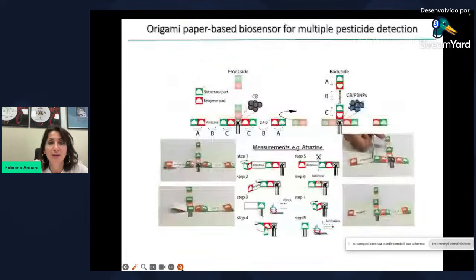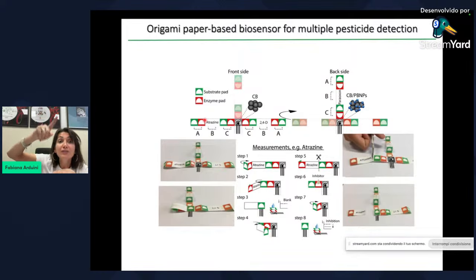This is the concept. We have 3 strips, and in each strip there are 2 couples of pads, one containing the enzymatic substrate, the red pad, the green pad, and one containing the enzyme solution preloaded. So how do we make the measurement in this case? We move from lateral flow configuration to vertical flow configuration thanks to the origami design. And this is mainly possible only using paper and using electrochemical detection.